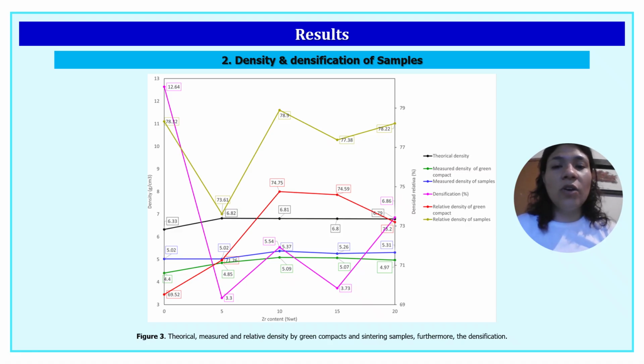This occurs because as more of the base alloy is replaced with the new element, the theoretical density tends to approach the density of that element. This phenomenon continues until the solubility limit of the element in the matrix is reached. A reduction in the densification of the sintered samples containing zirconium can also be observed when compared to the alloy without zirconium. This was mainly attributed to the addition of particles larger than the powders forming the matrix, which may have affected atomic diffusion and the ability of the grains to achieve good coalescence.